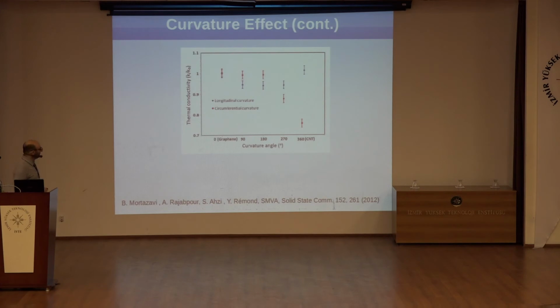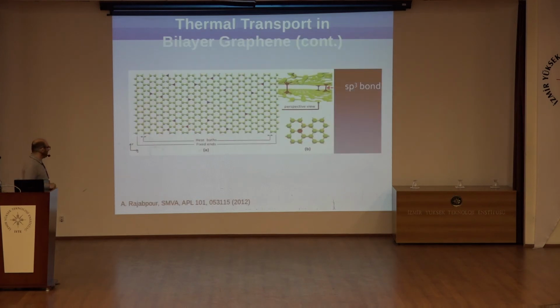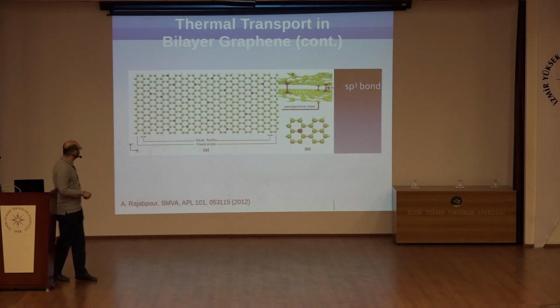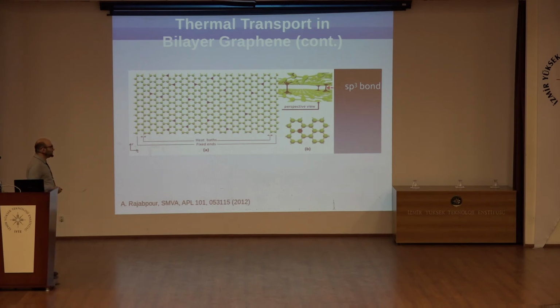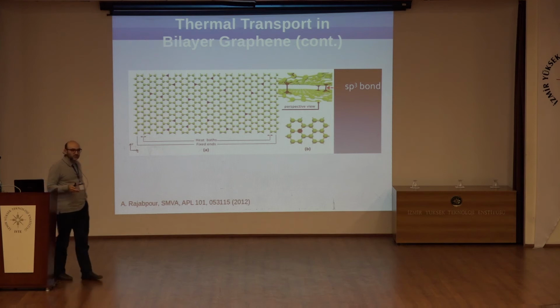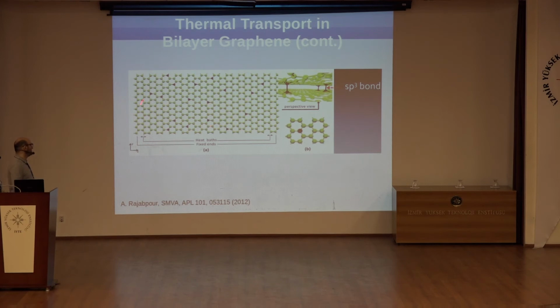We showed that by creating a special amount of local curvature inside the system, it is possible to get, or at least vary, the amount of thermal conductivity in the graphene case by a factor of 30%. It means that it is possible to tune thermal conductivity locally and let the system come back again.